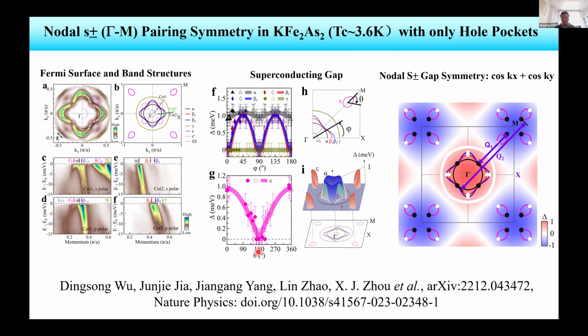But from our latest ultra low temperature ARPES measurements, we can clearly see the Fermi surface and the band structure. We clearly observed the momentum-dependent gap structure for the 4 Fermi surface sheets, 3 around the gamma point and 1 around the M point. So eventually we get the gap structure, and I think our measured gap structure, together with the locations of the nodes, is consistent with the nodal s plus minus gap symmetry. Here the gap sign changes from the gamma point to the M point, plus and minus. So that's the s plus minus symmetry.